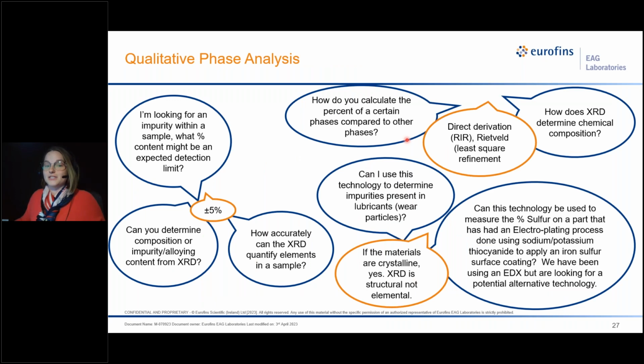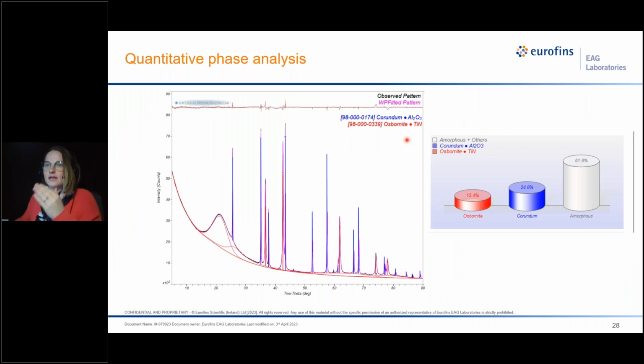Next, after what is it, the next question is how much is there? Our typical detection limits are plus or minus 5% weight percent. And again, this only works if you know all of the compounds within your sample. In a quantitative phase analysis, there are several kinds of analysis you can do. You can do what's called direct derivation, where you're purely using the area under the curve, essentially saying there's this much area for these peaks with this phase, and this much for that phase. That's a good back of the envelope. A lot of people ask about Rietveld analysis, which is essentially using least squares refinement, where the program doing the refinement knows the actual crystal structures.